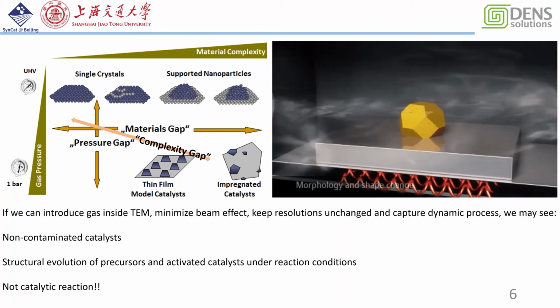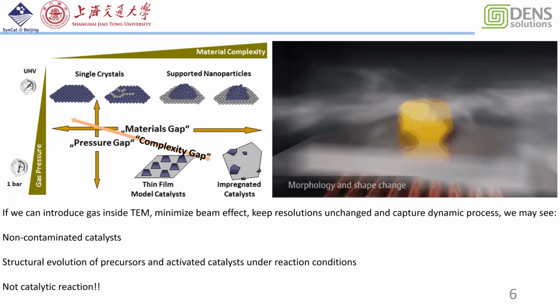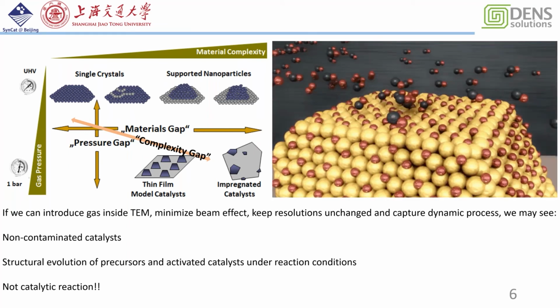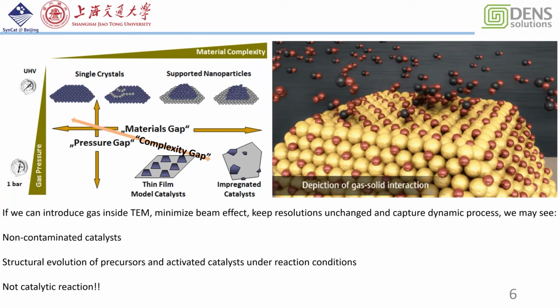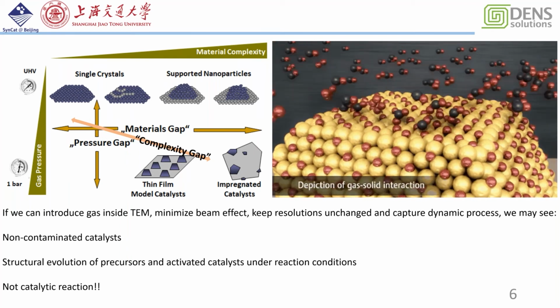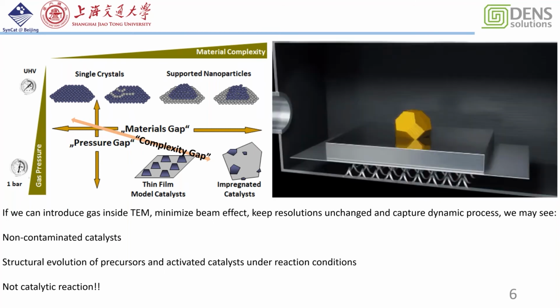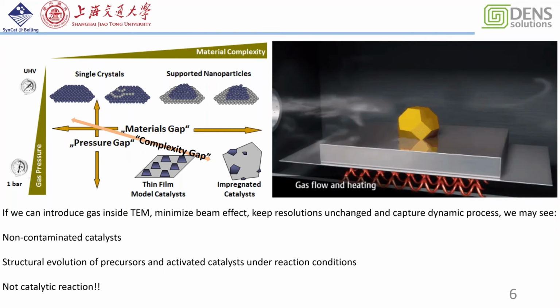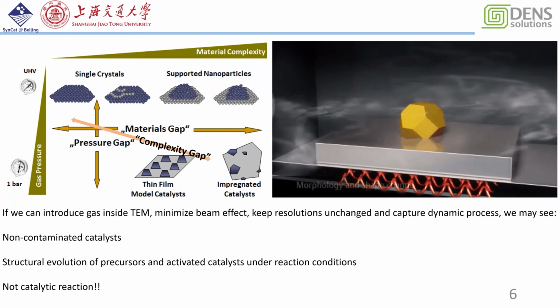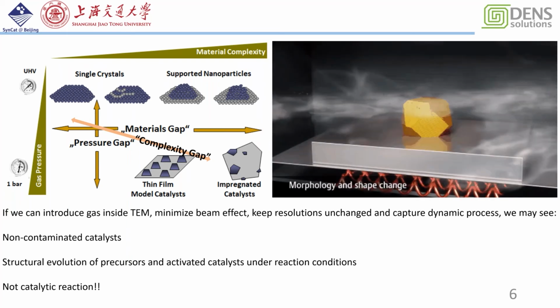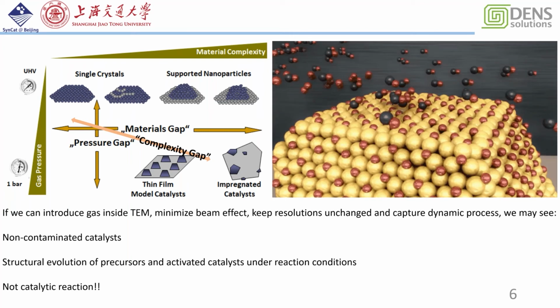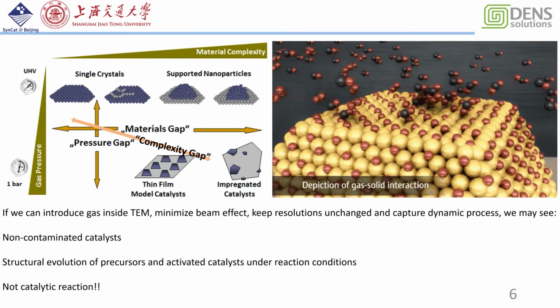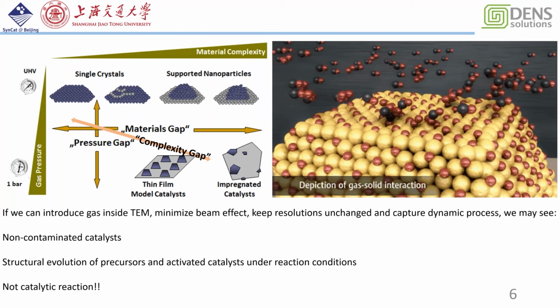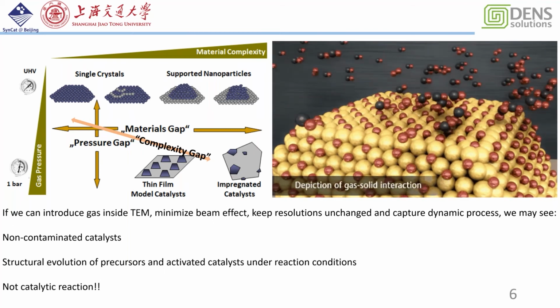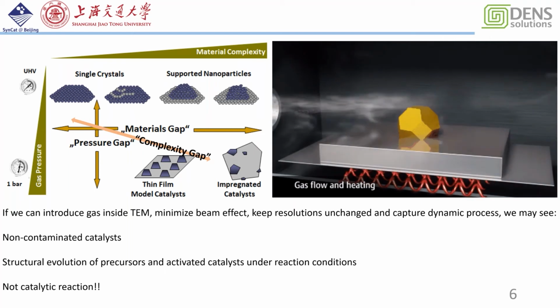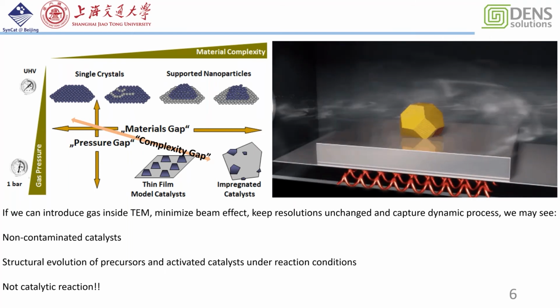Using this technique, we definitely can see the non-contaminated catalyst. It means that if we treat the catalyst in a very careful method, the catalyst will not be contaminated by oxygen and the outer atmosphere. And we can see the catalyst removed from the chemical environment to understand what it is before and after reaction. And definitely we can see the structure evolution of the precursor and the catalyst under reaction condition at the nanoscale and even sub-angstrom scale.